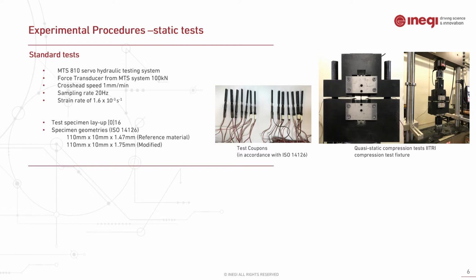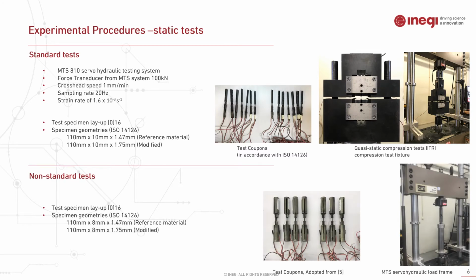In the case of the static loading regime, we have a standard test procedure following exactly the ISO standard, and we call these the standard experiments. And then we have non-standard tests, which use test fixtures compatible with the dynamic instrument. The goal was to study the size effect and also to see the difference between the test fixtures.